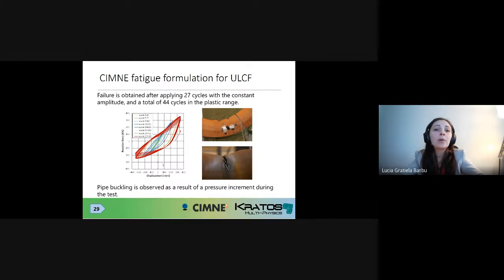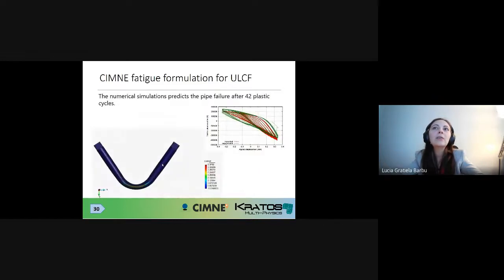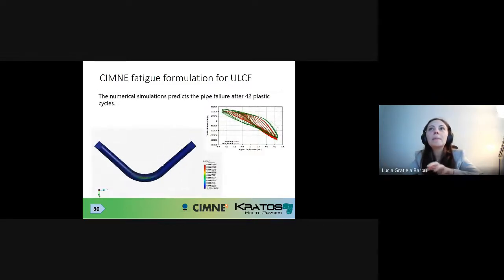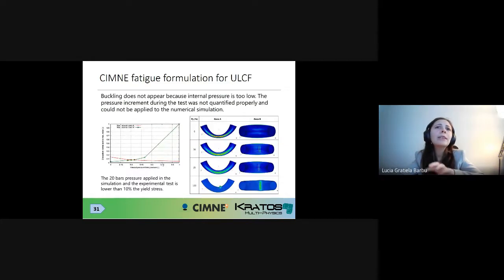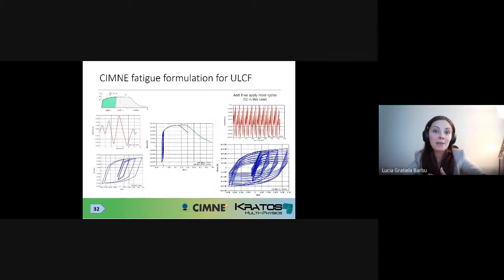Okay, now results regarding this. We used it for a project in oil and gas for the piping industry. And here you can see, for instance, an elbow which was subjected to cyclic loading with some internal pressure. You can see the adjustment between the numerical and experimental behavior, which was quite good. However, we saw that regarding the failure mode, there was a slight difference because of the level of internal pressure. And this motivated us to do a whole analysis of how the failure mode changed with the level of internal pressure. You can see more results in the publications that I mentioned. I don't want to insist more here because I have a lot of news on other things.